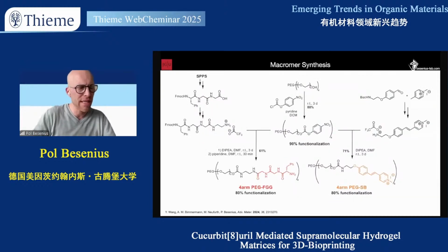A tiny little bit of synthesis is actually fairly simple. Peptide chemistry is our daily business, so making a tripeptide is very simple. What is shown here again is the solid phase peptide synthesis approach to make an FMOC protected phenylalanine. We use star PEGs, as I already mentioned, four-arm star PEGs, which are activated via chloroformate chemistry, and then turned into urethanes via the nucleophilic amine of the tripeptide that is still FMOC protected, and then deprotected